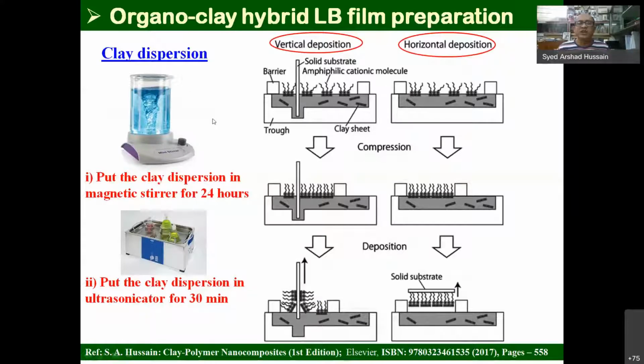For preparation of the organo-clay system, what we do is prepare a clay dispersion in water, following magnetic stirring, then ultrasonication. Then we put it in the LB trough, then we put some organic material, mainly cations, on the surface and allow time so that they can come onto the surface through cation exchange reaction or electrostatic interactions. Here we have shown. Then we compress, then we deposit. So in this way we do these things.